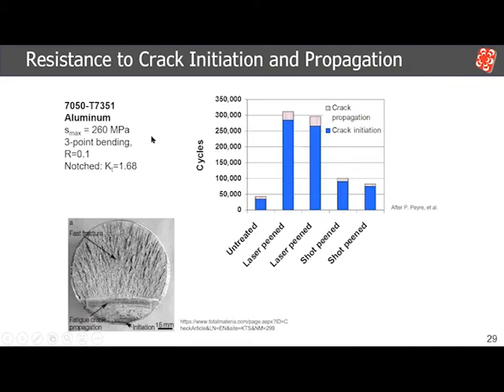And looking at the same stress level that I gave as an example, you can see the baseline is around 50,000 cycles. Shot peening was able to push it to 100,000 cycles, whereas laser peening was able to push it to 300,000 cycles. And the majority of that improvement lies in the ability to delay the crack initiation side of things.